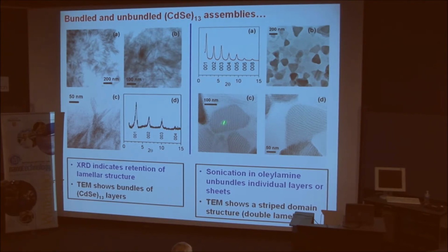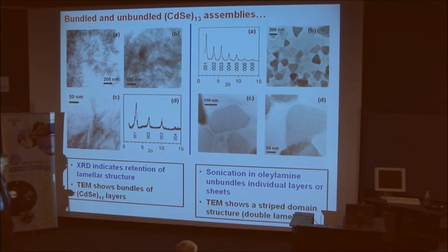We argue that the CdSe 13 nanoclusters are in the dark regions of the domains, and that in fact it's additional amine bilayers that are separating these striped domains from one another. And significantly, the width of these striped domains is 7 to 15 nanometers, which ultimately turns out to be the width of the belts. And for the material that remains bundled, you can see that the lamellar structure really sharpens up and has a much longer range periodicity.